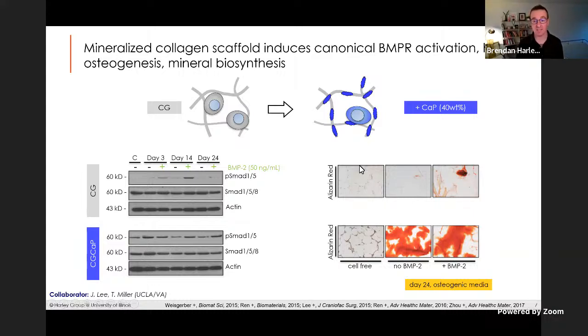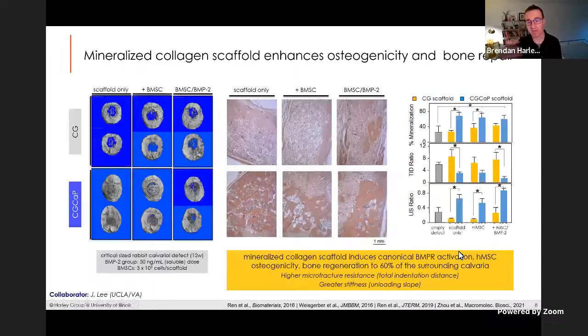You can add in, the scaffold on its own, you can add in cells and this BMP2 growth factor, you see a little bit of bone formation. Whereas on the bottom, our mineralized scaffold, you add cells just on their own and you get lots of bone formation. We can add in the growth factor and we see the same amount. We then went into animal models.